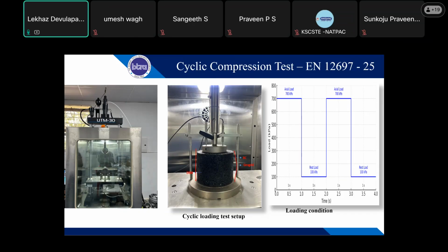I just want to show the image here. This was an SCB test, the semicircular bending test. We can change this attachment, and this instrument has the facility to do all kinds of tests like resilient modulus, dynamic modulus, triaxial, semicircular bending, even the Marshall and the cyclic compression. We just need to change the attachments. Similarly, our cyclic compression test attachment has been placed inside this one, having a diameter of 100 mm. A solid disc is placed on this one, and then the cyclic loading is applied.